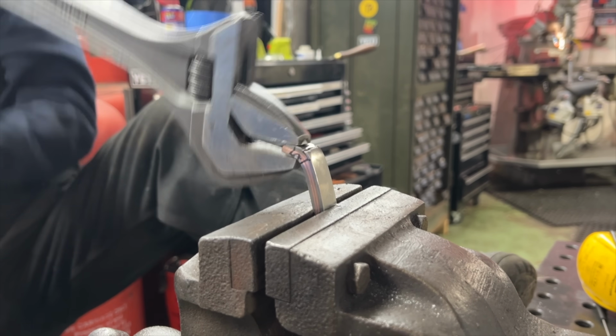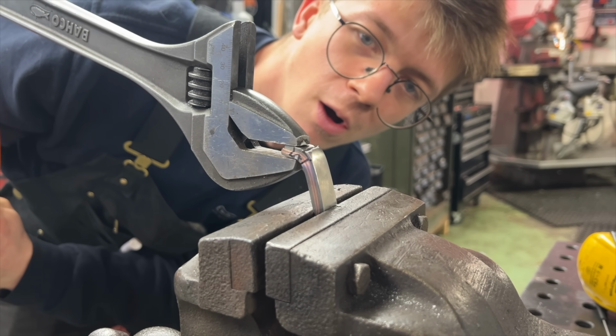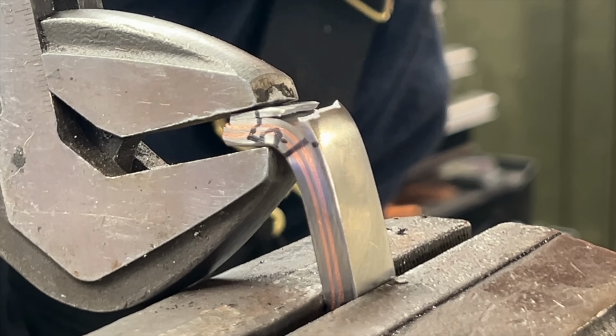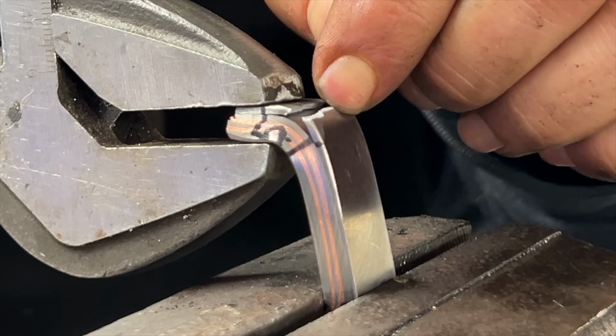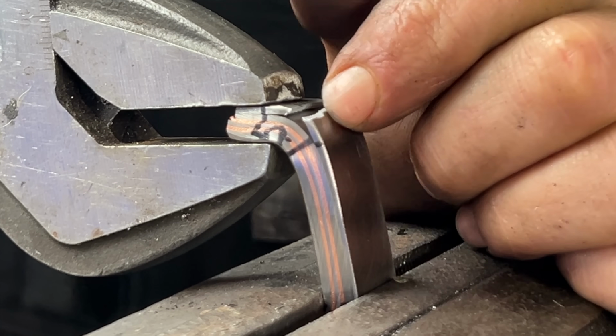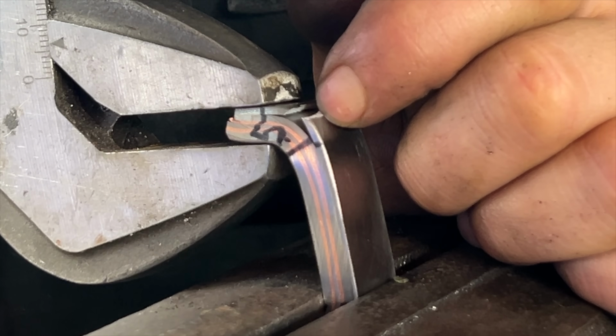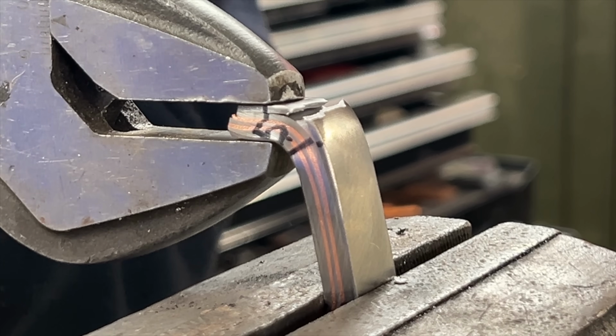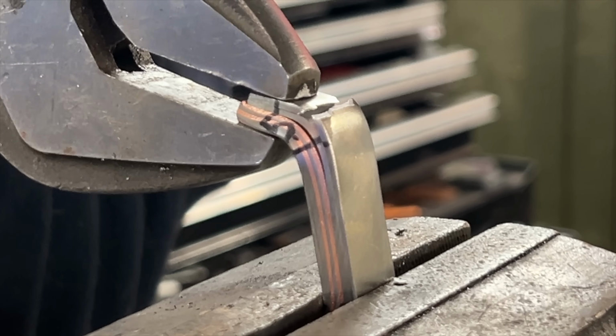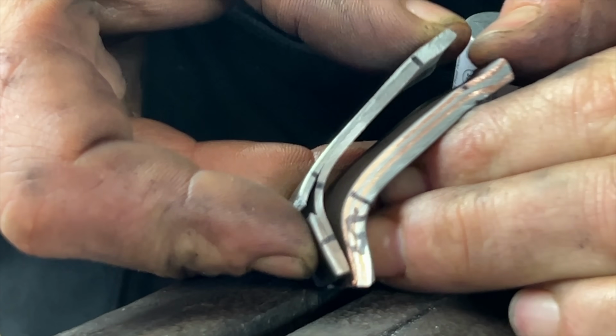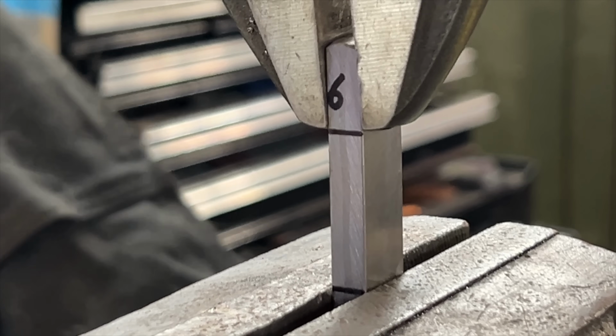5. Oh. 2mm copper was my favorite last time. Not good. That's the grade 5 titanium snapping. That actually has nothing to do with our titanium to steel bond. It has nothing to do with our interlayer. That's just the grade 5. If I go back a little bit, yeah, interlayer. I believed in you. 6, the zirconium.